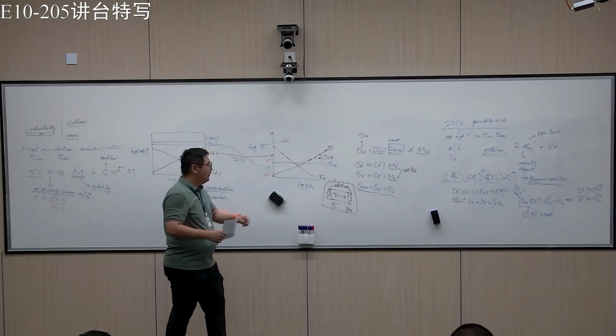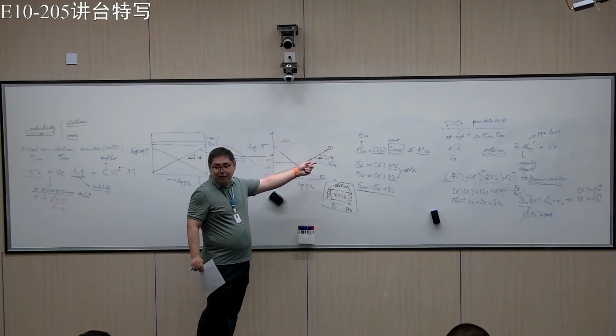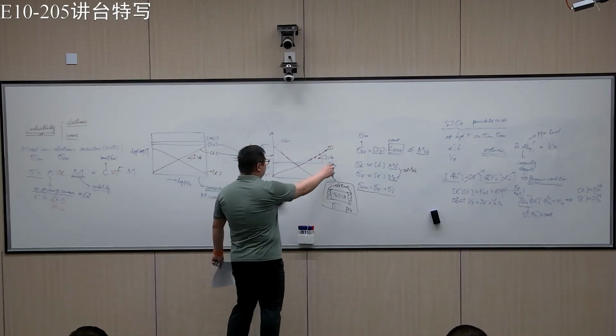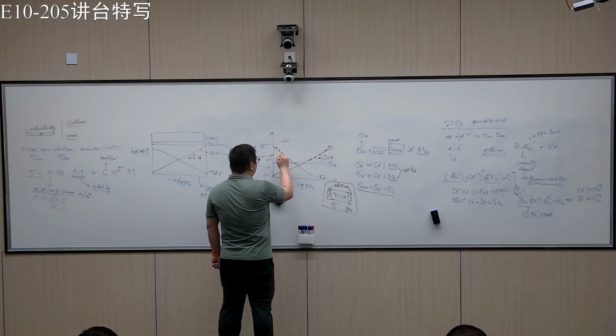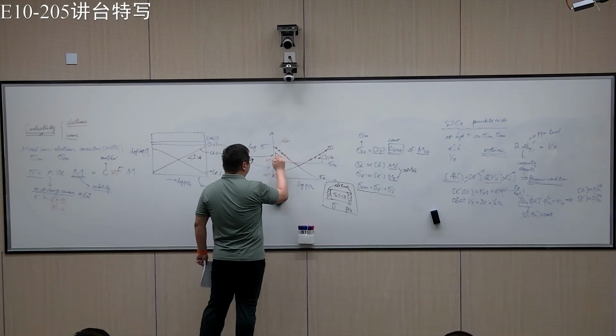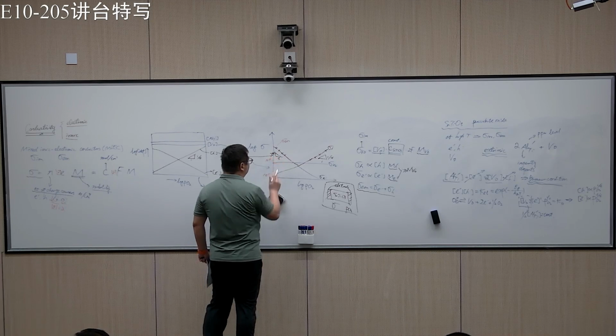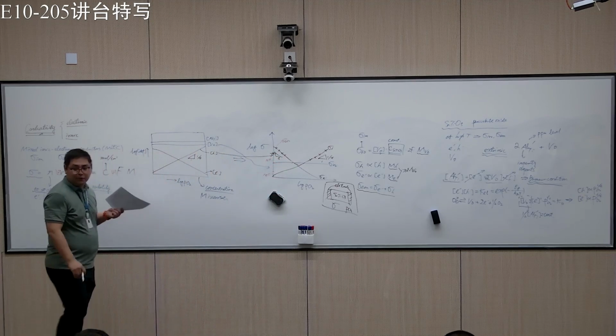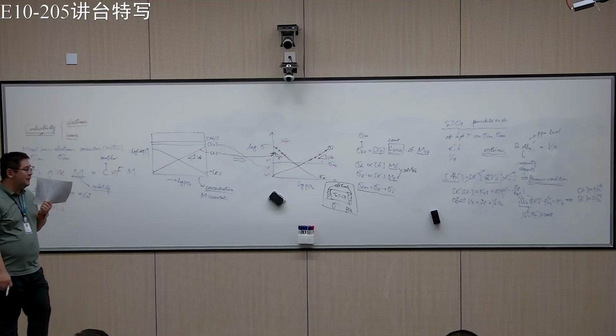Okay. For the high pO2 regime, we have really p-type semiconductors with the slope of 1/4, right? For the other regime, we have minus 1/4. Okay. So basically, experimentally, it's really something like this.